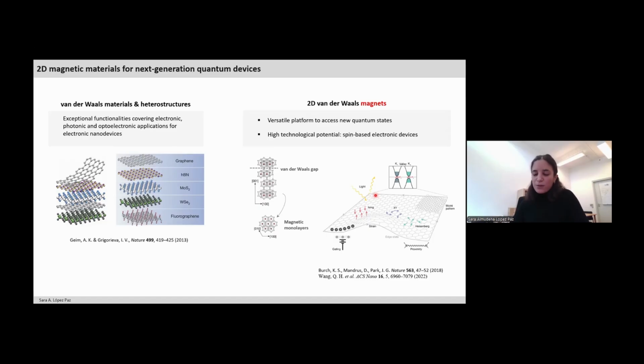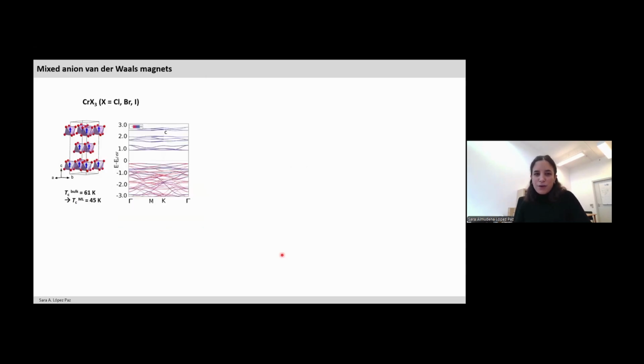And when looking at what was done in terms of materials chemistry, or what was the material database that we were exploring at the moment, I realized that most of the work was actually focused on transition metal trihalides, which can be made for several halides, and they are all magnetic, but actually they are very ionic, meaning that they show pretty flat bands, meaning that the electronic conductivity is very, very low. So if we want to implement this material in a device and control it, for example, via an electric field or gating, we would like the electrons to conduct.